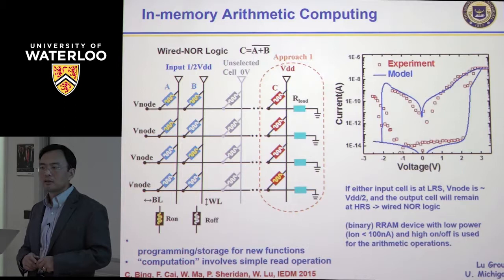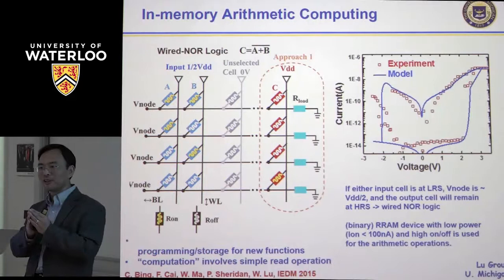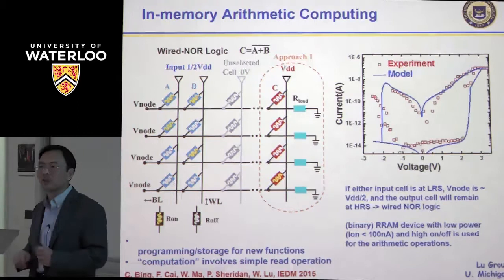So the insulator will not break down? That's a very interesting idea. When they break down, normally they have a defect, like a pinhole. When you have a very thin film and a very small device, the breakdown field actually goes up. The thinner you make the film, the higher the breakdown voltage typically is.